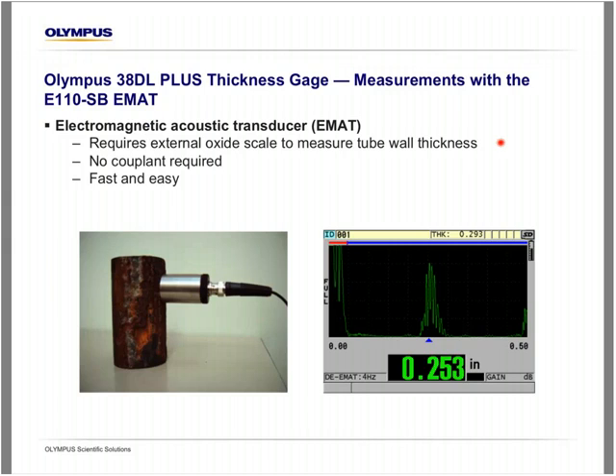It doesn't require couplant. It's a non-focused signal, so it's going to be relatively insensitive to small internal pits. The accuracy is about plus or minus 10 thousandths of an inch, or about 1/4 millimeter. And the minimum thickness is about 80 thousandths of an inch, or 2 millimeters. So it's really just an initial screening tool.